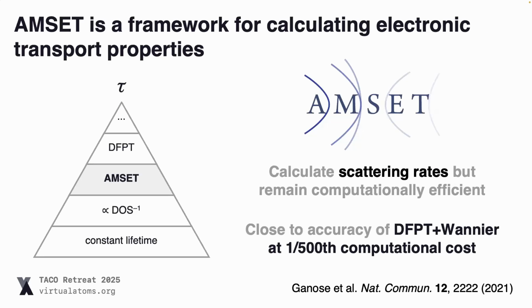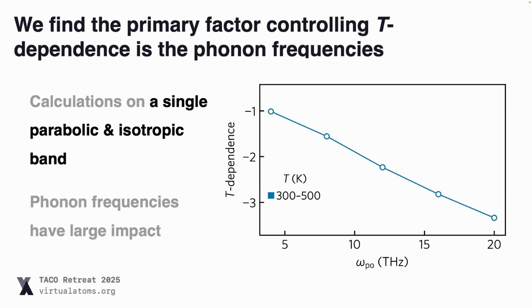But we wanted to understand exactly what was going on. So then we turned to our AMSET method. The first thing we did is take a very simple model, a single parabolic band, and one of these simplified scattering mechanisms, the polar optical phonon scattering, and we adjusted one single parameter, which is the polar optical phonon frequency. And we found that just by varying that one parameter, you can essentially get the temperature dependence to vary across this -1 to -3 range. If you do this at higher temperatures, you see the same effect, it's just less pronounced. And so we really think, and it's very obvious when you look in detail at the expressions for mobility, that it's the phonon frequencies which are central to the temperature dependence rather than the scattering type itself.